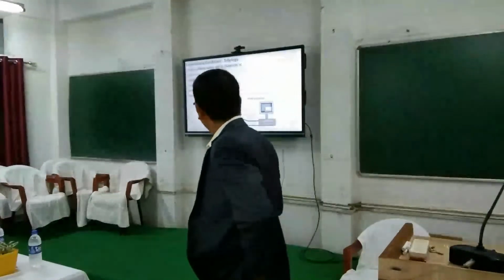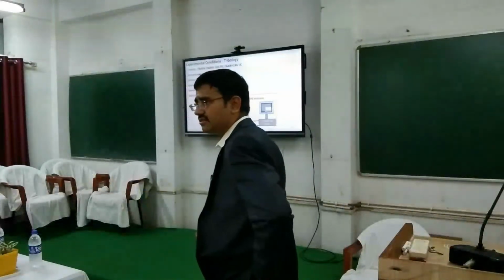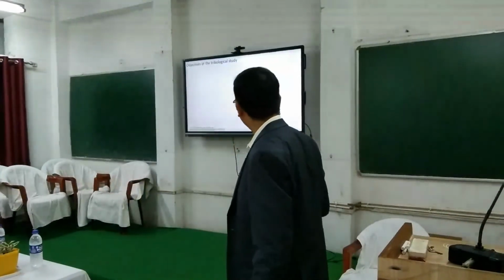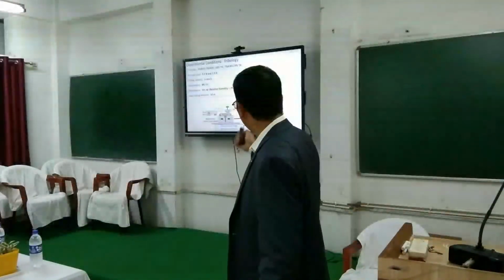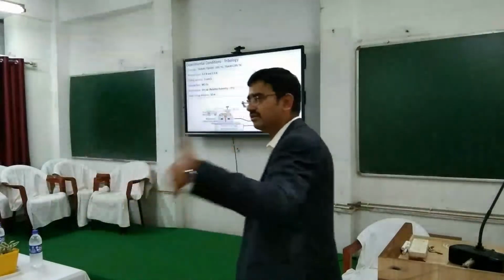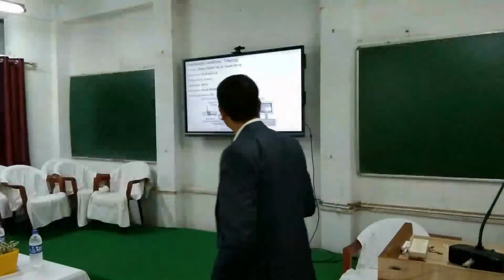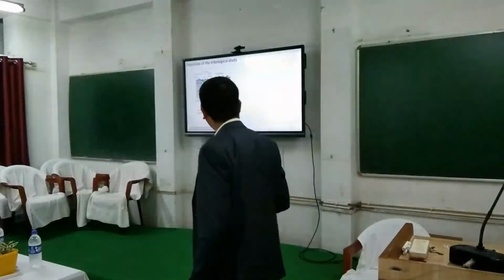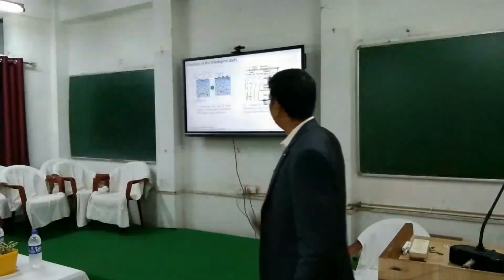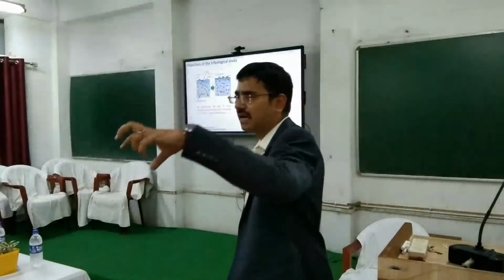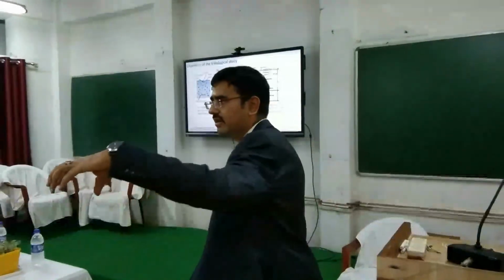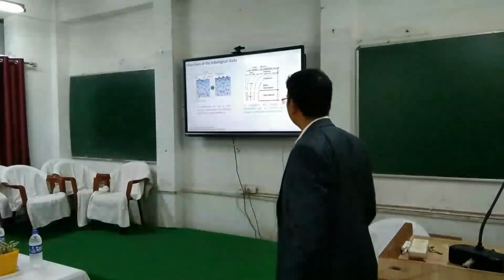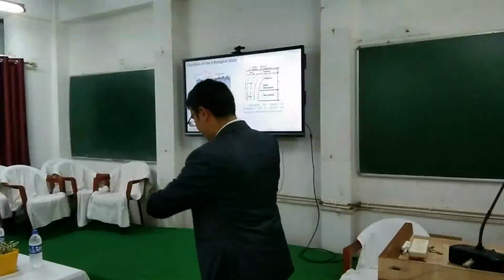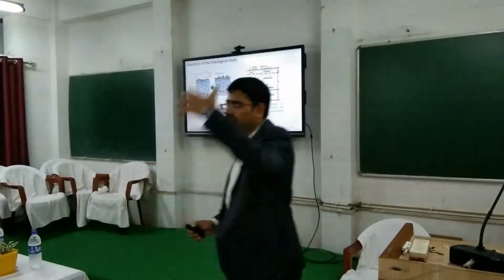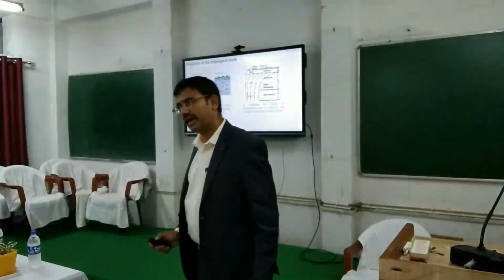Once we did it, we actually did wear tests. That's a standard tribometry test where we had a ball that slides and then we determine how much material is being lost. So we had two objectives here. Basically, one, to see how this second particle reinforcement, that is titanium carbide particle reinforcement, will improve the tribology of the materials, and second, how the microstructure below the wear track actually deforms.